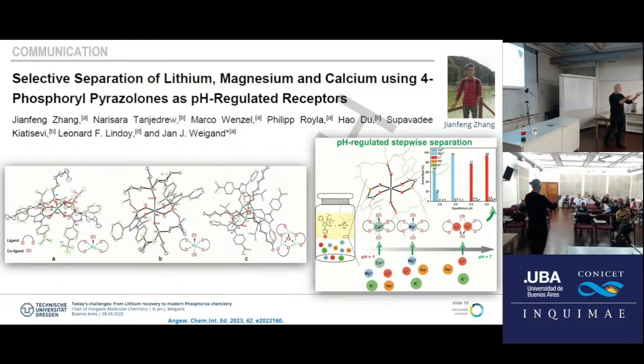Now, if you go to the Atacama desert, for example, and you want to use those brines which they recover there, you have a lot of calcium and magnesium. So what you're going to do, you make it as caustic as possible in order to separate magnesium hydroxide and calcium hydroxide. This is very expensive. You have to recrystallize, you have to purify. You need the sun for a long time to dry out, to crystallize in the end your lithium, and then you separate it in the end as lithium carbonate. As I said, it takes up to 24 months.